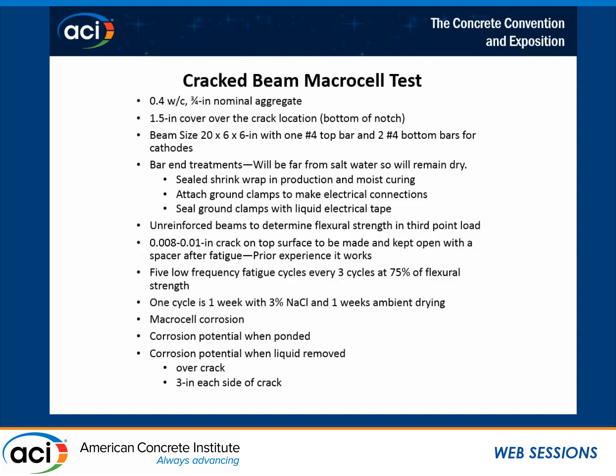We had unreinforced beams to give us an idea of what flexural strength we had. The idea was that we would crack them to get the right crack size, but later on, every few months, we'd put them into a fatigue cycle at 75% of their flexural strength. So that was a pretty substantial fatigue, and you didn't have to do a lot of cycles at 75%. And that would reflect real life, where you're going to have fatigue in a structure.